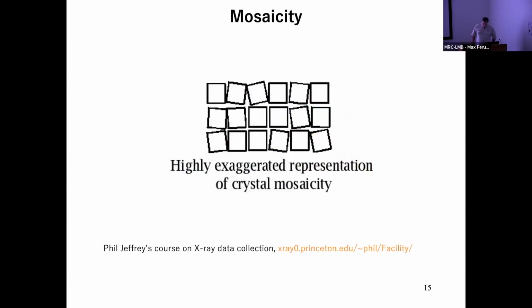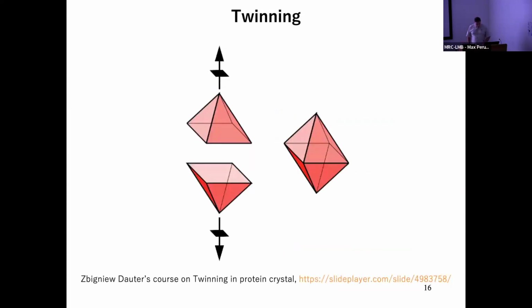A common issue among crystal lattices is mosaicity, a poor alignment between the unit cells. Mosaicity broadens the diffracted beams and lowers the signal-to-noise ratio on the detector. Another crystal pathology occurs when crystals are made of two or more lattices in different orientations, which can prevent solving the structure. Shown here, a most straightforward example of twinning where a crystal is formed with two pyramid structures in opposite orientations. But that's not going to make the data processing easier.